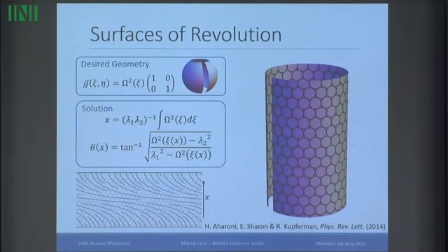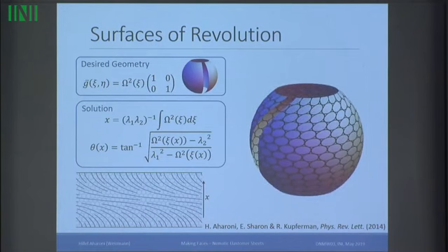They all deform into the same ellipse with factors lambda 1 and lambda 2. However, the direction depends on my director field. So circles in the center would deform into horizontal ellipses. Circles on the sides would deform into vertical ellipses. Everywhere it would be along this director field. And once all of this happens at the same time, my flat geometry becomes the geometry of a sphere, which is what I was trying to make.